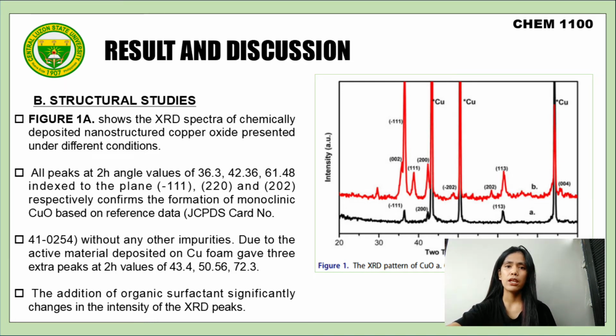All peaks at 2θ angle values of 36.3, 42.36, 61.48, corresponding to planes -111, 220, and 202 respectively, confirm the formation of monoclinic copper oxide based on reference data JCPDS card number 41-0254, without any other impurities. The active material deposited on the copper foam gave 3 extra peaks at 2θ values of 43.4, 50.56, and 72.3. The addition of organic surfactant significantly changes the intensity of the XRD peaks.